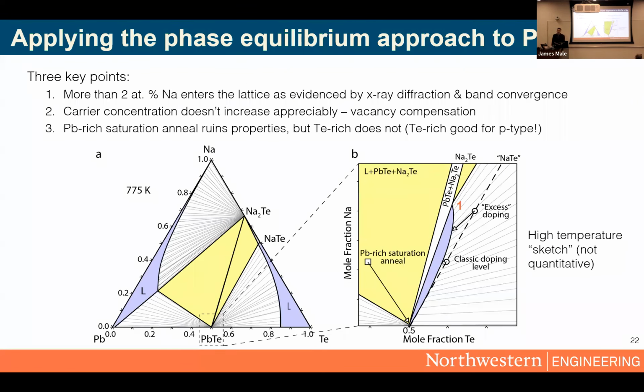Okay, so keeping that all in mind, we can draw another one of these ternary phase diagram sketches. And this one is much more of a sketch because we have a lot of trouble understanding exactly how much sodium is frozen into the lattice here. But there are a couple key points that let us draw the shape of this single phase width. The first is that we have more than the supposed classic 2 atomic percent sodium at high temperatures in the lattice, which means our phase width should extend beyond that classic doping level.